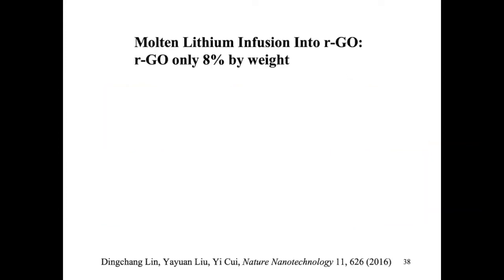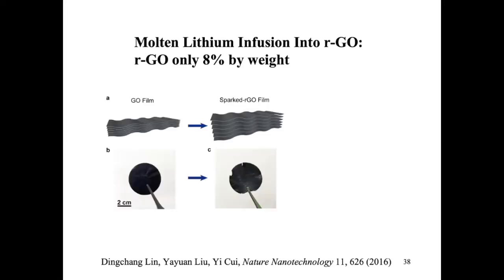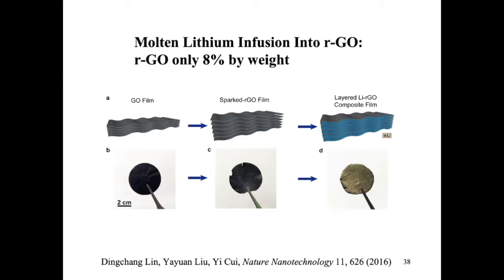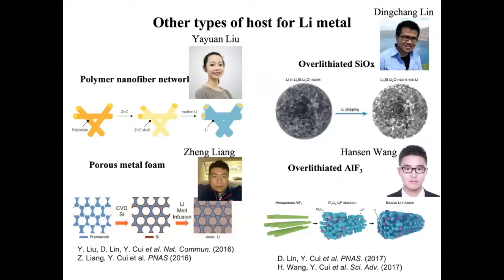And this reduced graphene oxide, the weight is a very small amount, only 8%. You can now embed lithium between the graphene oxide layers. This functions as the host to stabilize lithium, and then if you strip lithium away, its whole volume will not collapse to completely empty. Indeed, if you don't strip all the lithium completely away, you can hold the volume of this host right there, fix its thickness. This helps you to increase the stability of lithium metal. So I will jump through this.